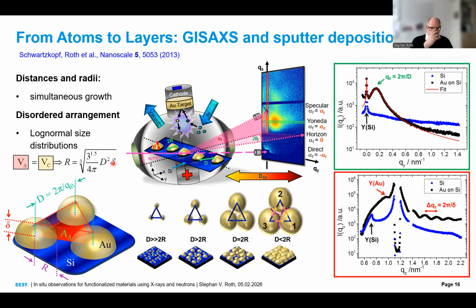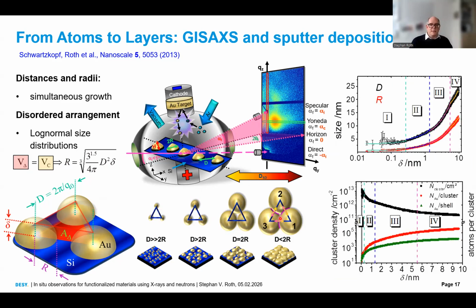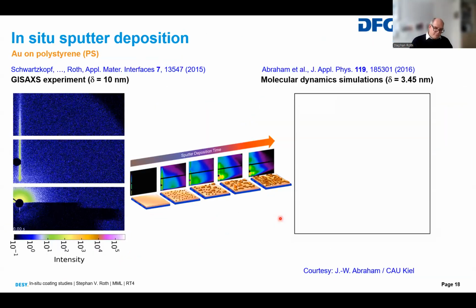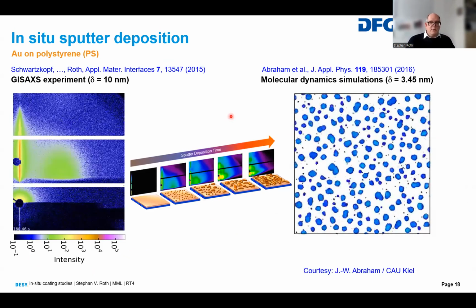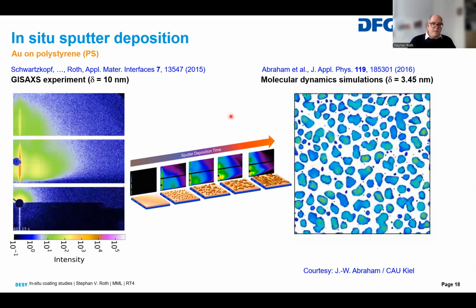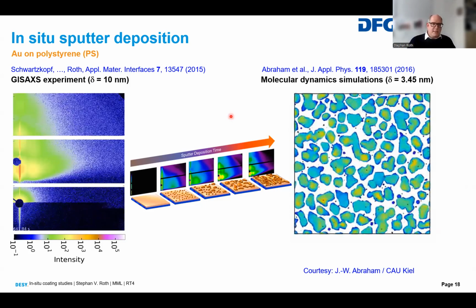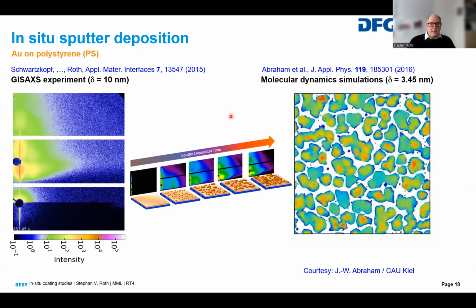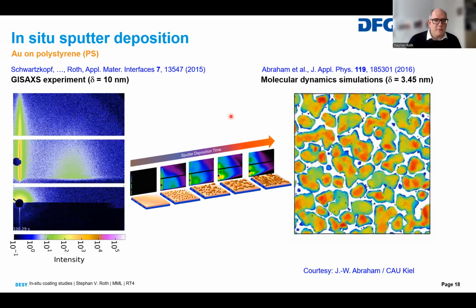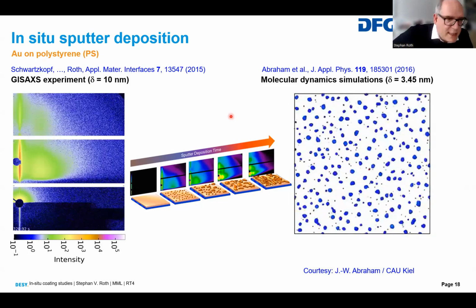And this is just one model. We show here the typical nucleation regime, the diffusion regime, and then the percolated regime, and finally the regime where the clusters only grow in height after percolation. This we can deduce with this simple model. And on this slide here, just to show you on the left side, this is a video from the different GISAXS images, just one after the other. This is a slow GISAXS experiment, 10 frames per second.